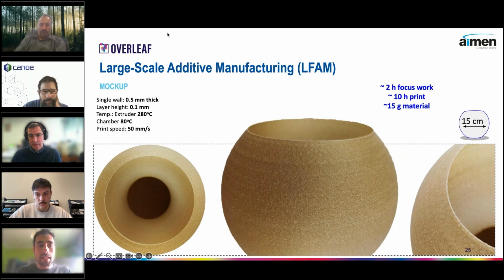And just to give an idea of the problematics that this large-scale printing is bringing, let me show you this super short example. Here, what you are watching is a mock-up of the tank. It is like we are taking the huge tank, reducing it, and trying to print it. Here you can see that we make a reduction of 10:1, so we are printing 0.5mm thick walls with 0.1mm layer height, using the same printing conditions: around 300 degrees Celsius in the extruder, a chamber at 80 degrees Celsius, and a printing speed of 50 millimeters per second.